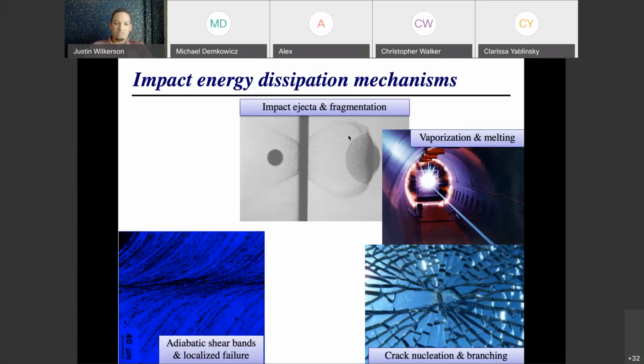In a more ductile material, you have a couple common failure modes. One is adiabatic shear localization. So what's happening here is that this is primarily a shear-dominated loading, and you can see that the material is plastically flowing in a shear way, but it's localizing into a small band. And the reason that we tack on this word adiabatic here is because this localization is accelerated by heat. So if you start to get more plastic deformation in a single region, then that region will heat up more. There will be thermal softening in that region, which will make that part of the material weaker. And because it's weaker, you'll have even more deformation in that region of the material, and you kind of get